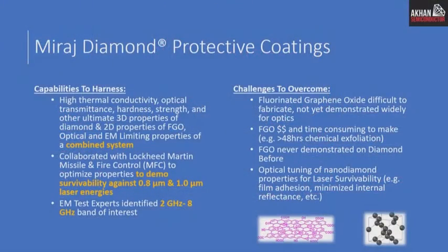So with this, we proposed 6 months ago our Miraj Diamond Protective Coatings. Now, diamond is somewhat known to be an extreme material. It has the highest thermal conductance, the highest hardness, some other extreme properties which make it very favorable for electronics application. But perhaps a lesser known material, a two-dimensional material, fluorinated graphene oxide, also has these extreme properties. Very high Vickers hardness, very high thermal conductance, very high thermal shock resistance. The combined system of which promises to offer all of the necessities needed to protectively coat these directed energy facing